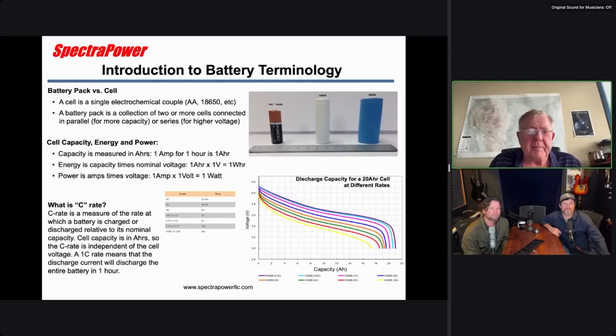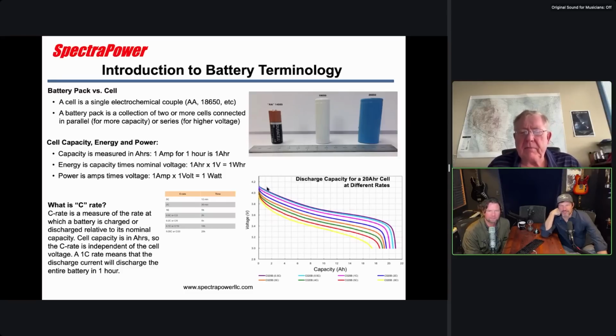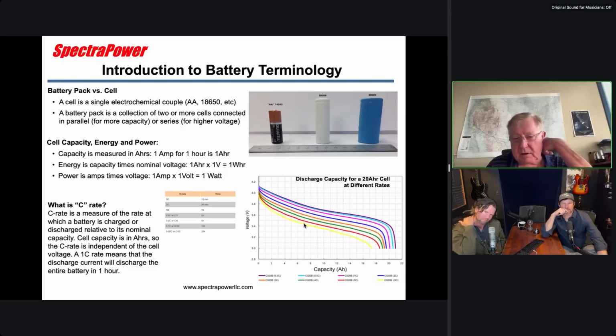And so I say nominal voltage because if you look down here on the right, this is a typical discharge from a lithium-ion cell. So you get voltage drop over time. Well, it's discharging. If you didn't discharge, it would stay flat. So this is a discharge curve. And you can see down here the capacity in amp hours, and these are at different rates. Let me explain rate, and then I'll show you this curve more.